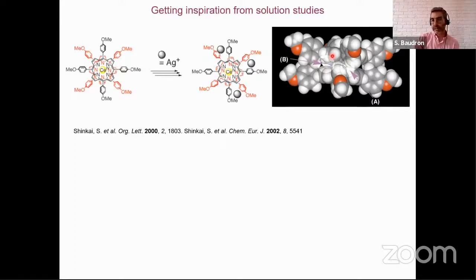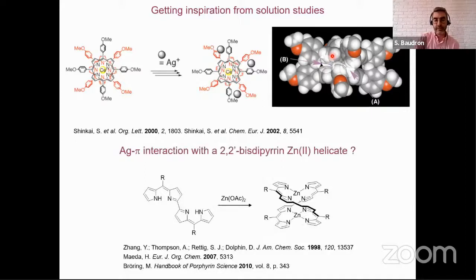So we wanted to redesign our ligands, and to do that, we thought of going from dipyrrin to 2,2'-bis-dipyrrin ligands. This type of derivative has been studied by the groups of Dolphin, Maeda, and Bröring, and they consist of two dipyrrin fragments that are directly connected at the position 2 and 2' by a carbon-carbon bond. Upon complexation of zinc 2 cations, they tend to form binuclear helicates. So you have one strand here in the front and one strand in the back.